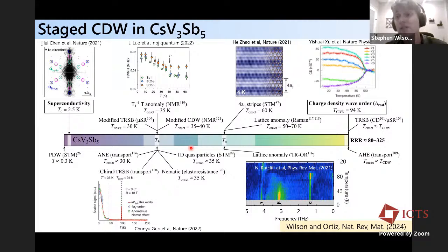And as you continue cooling the system, around 35 Kelvin or so, there's a second stage where you see the onset of quasi-one-dimensional features in the band structure as seen via quasi-particle interference spectra and STS measurements. NMR measurements also see some sort of local changes in the vanadium and antimony environments. And then as you continue cooling the system even further, before you hit the superconducting phase, there's a report that you have an additional charge modulation at a wave vector like the so-called 4/3 A phase, which is reported to be a signature of a pair density wave instability that modulates the superfluid density in the superconducting phase.